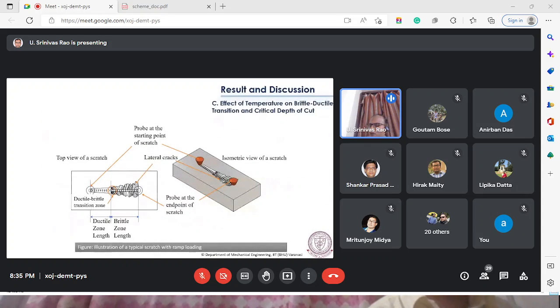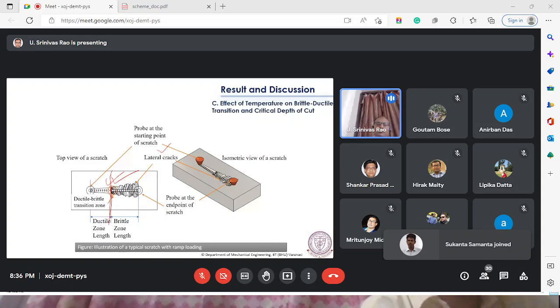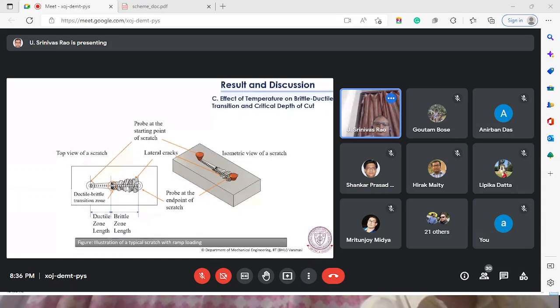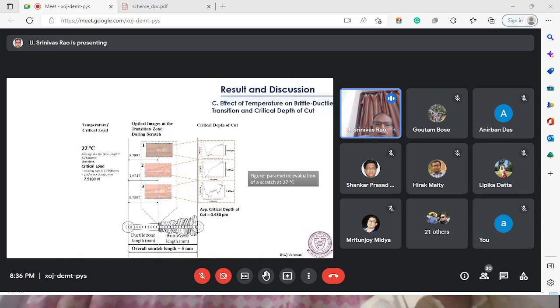Through that, I will show you one more graph. These details, this is one schematic diagram. So when the scratch is going on with different loads at different temperatures, gradually the scratch width and depth are increasing, and there is a point where the ductile brittle transition occurs. After that, the micro cracks or lateral cracks are more visible. So this point is demarcated. This gives the point of critical depth. And how that critical depth is increasing when we have elevated temperature was the main point of study, and that is how it is obtained at different places.